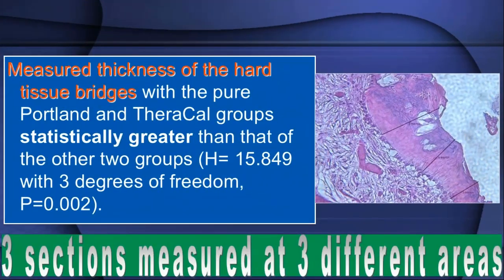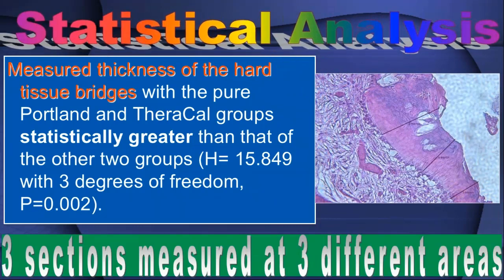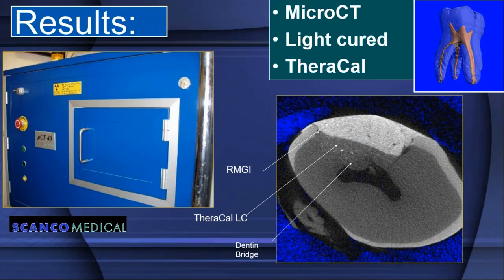And here's the statistical analysis on it. Three sections measured at three different areas, exactly as you're supposed to do it for the FDA. And at the time, we were the first study to actually follow the FDA recommendations. We were also the first study to use micro-CT, so we could look at it three-dimensionally with Dr. Stuart Stock from Northwestern. And this was all done blind, of course, utilizing his micro-CT unit, as you see there at Northwestern, to form these really wonderful three-dimensional images of the bridge formation.